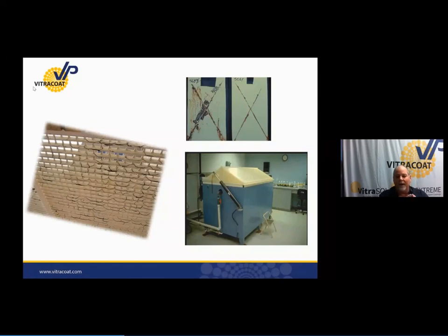What's pictured here right now in the top is panels run with an ASTM B117 standard. The one to the left has a huge amount of creepage underneath the scribe. The one to the right performed pretty well. The bottom right is a salt spray chamber where those panels were tested. The one to the left is a part that was tested with the same powder on the top right panel and performed horribly in the field.